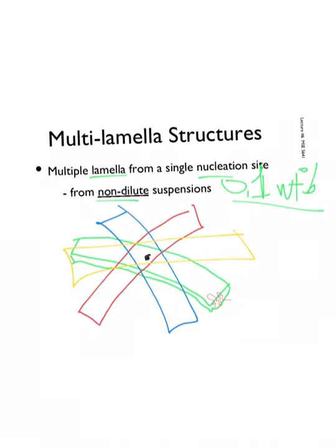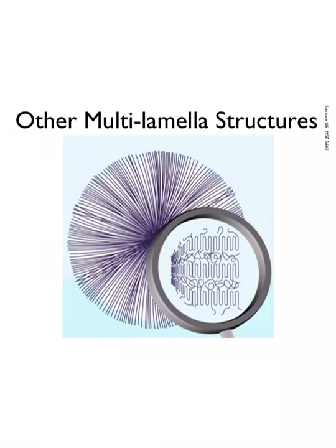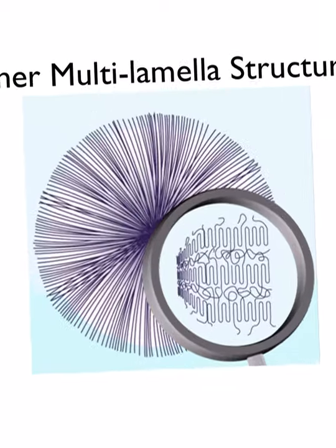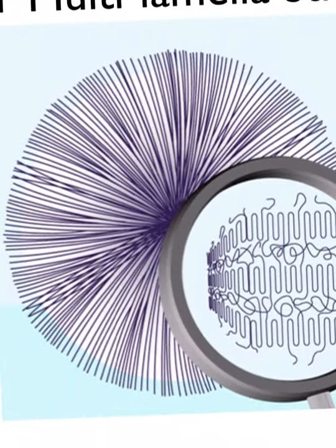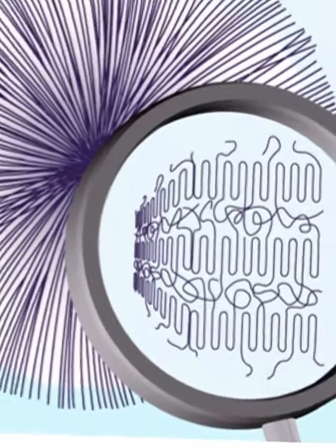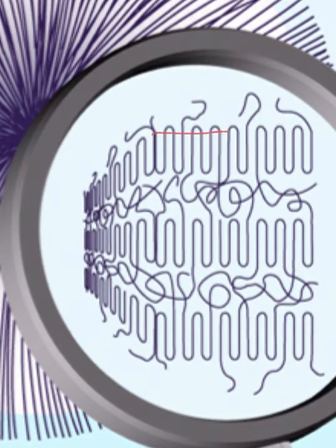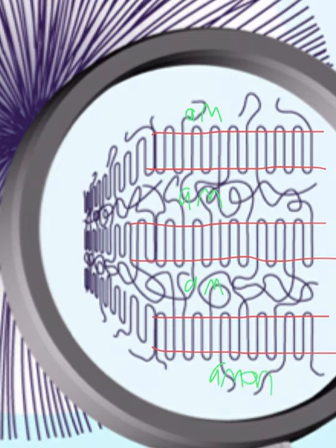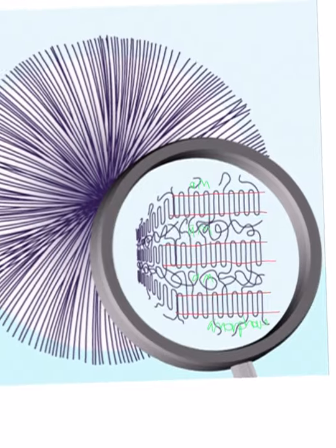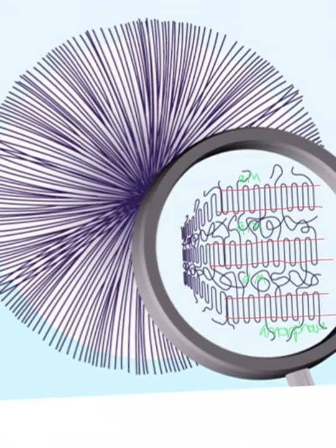So this is slightly more concentrated. In reality, of course, if we go toward more of a melt structure, this is attempting to show you the spherulite on the outside growing in this totally amorphous medium. But if we zoom in on it, again, same rules apply. We have crystalline structures defined by these red lines, and they're all the same inside the red lines. And then outside of that, we have amorphous content. Amorphous content, amorphous content. Amorphous. I'll spell it out here. All right, so this is why even if we zoom out and we see those nice round spherulites growing in that melt, inside of that nice round spherulite, which consists of many individual single crystals, we have lots of amorphous content.